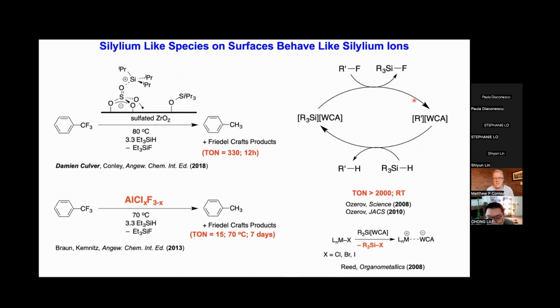So a silylium ion is expected to activate C-F bonds in the presence of silanes to make alkanes. And if you have our silylium-like species on sulfated zirconia, indeed, it'll do that for the activated products. And it's significantly more reactive than, at the time, the state-of-the-art heterogeneous catalyst, but significantly less active than what you would observe with a carborane anion.